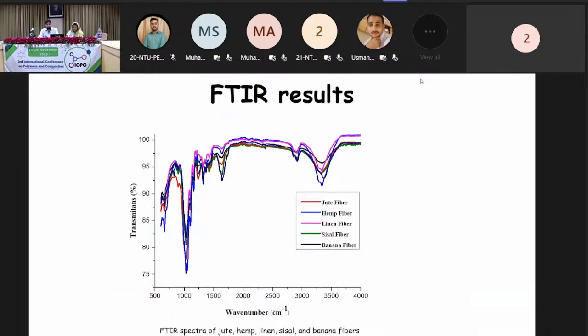Regarding the FTIR results, the OH stretching vibration is related to the broad peak at 3,000 to 3,600 per centimeter. The asymmetric and symmetric CH vibrations from the CH2 group of cellulose and hemicellulose respectively are represented by the peaks at about 2,900 and 2,850.